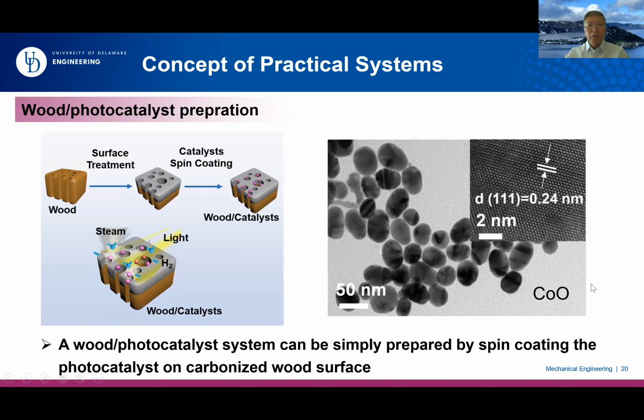All right, the preparation of this piece means integration of the wood and the photocatalyst. It's very straightforward, very simple, as the schematic shows here. You have a piece of wood and do some surface treatment like carbonization. Then you simply use a spin coating method to coat the catalyst into the pore structure of the wood. After that, you just put the piece under light, and you have steam generated. At the same time, you get hydrogen gas.